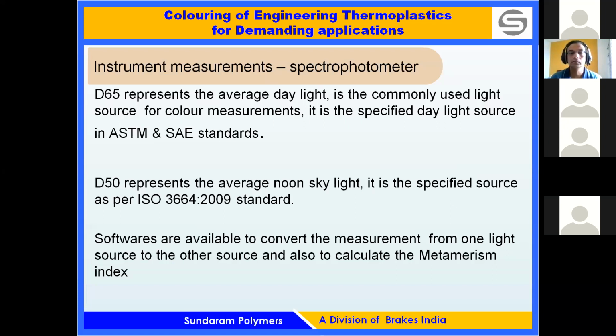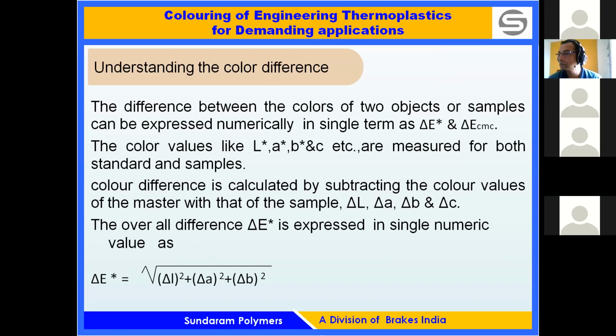So, understanding the color difference. The difference between the color of two objects or samples can be expressed numerically in a single term as delta E star and delta E CMC. These are two different sets of measurements, for the standard and the sample. Color difference is calculated by subtracting the color values of the master from those of the sample, leading to delta L, delta A, delta B. Delta E between the two shades is expressed as a single numeric value: delta E star equals the square root of delta L squared plus delta A squared plus delta B squared. This is a theoretical calculation. Nowadays the software can automatically give you the values of delta E star and delta E CMC the moment it measures the standard and the sample.